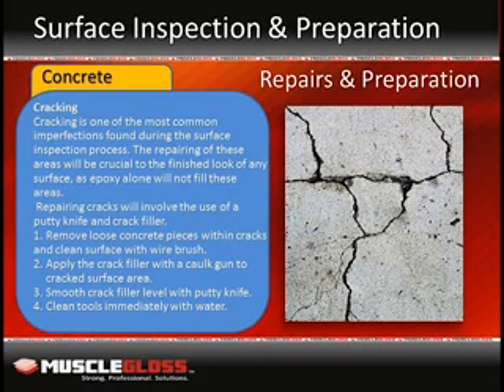Repairing cracks will involve the use of a putty knife and crack filler for cracks up to a half inch wide. Remove loose concrete pieces within cracks and clean the surface with a wire brush. Apply the crack filler with a caulk gun to cracked surface areas. Level crack filler with a putty knife. Clean tools immediately with water. You should let concrete dry before sanding or etching to ensure proper bonding and repairs will remain in place.